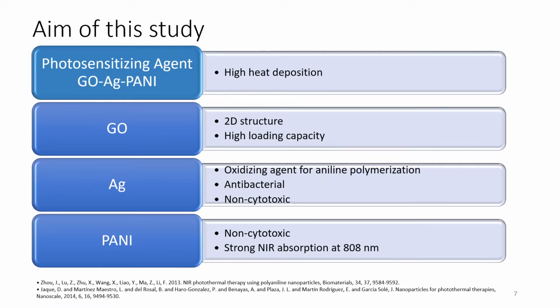So the aim of this study is to develop a photosensitizing agent with high heat deposition, and for this purpose we used graphene oxide for its two-dimensional structure with high loading capacity, and silver for oxidizing aniline, and also silver nanoparticles are antibacterial and non-cytotoxic. And finally we used polyaniline for mainly its strong near-infrared absorption at 808 nanometers, and also it is non-cytotoxic under concentrations of 0.1 milligrams per milliliter.